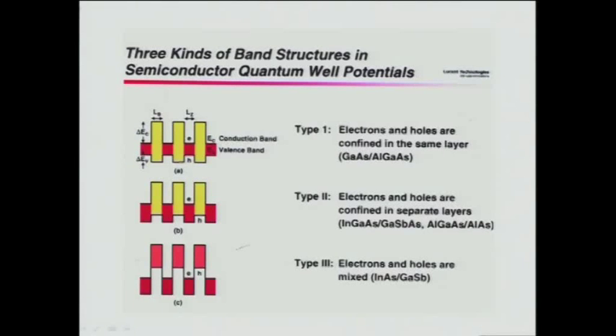And with superlattice structures, of course, we all know there are 3 different kinds of alignment. For instance, you have the type 1 alignment of gallium arsenide, aluminum gallium arsenide, where electrons and holes are confined in the low bandgap layer, in the same material, same layer. And then the type 2 is like in antimonide compounds, where the electrons and holes are confined in 2 different, separate layers. And finally, the type 3 is where the electron and hole are mixed, that is in the superlattice structure of indium arsenide and gallium antimonide.